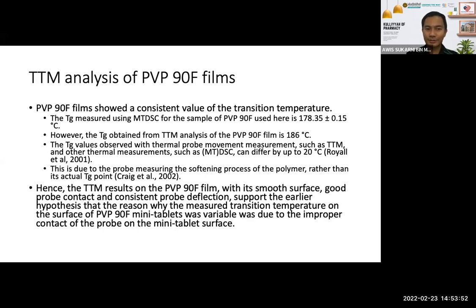But this is quite common, because based on the article by Royall et al. in 2001, he found that the Tg value observed with thermal probe measurements such as TTM and other thermal measurements such as the MTDSC can differ by up to 20 degrees. This is because the probe is measuring the softening process of the polymer rather than its actual Tg point. So that's why there is a difference in temperature between TTM and the DSC. However, the result showed a consistent value of around 186 degrees. So with the TTM, the result on the PVP film is very consistent, because the surface of the film is very smooth. So it basically justifies our hypothesis before.